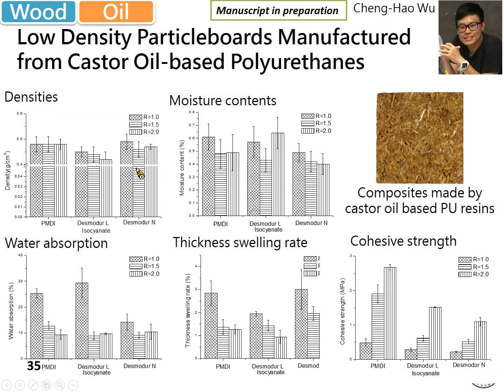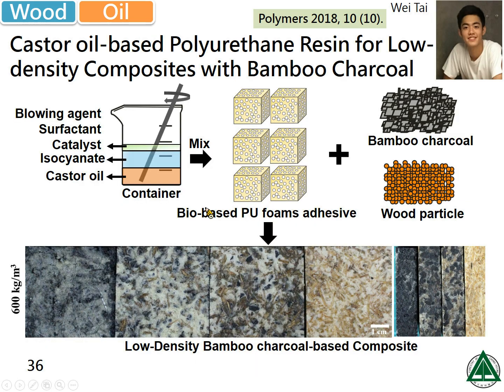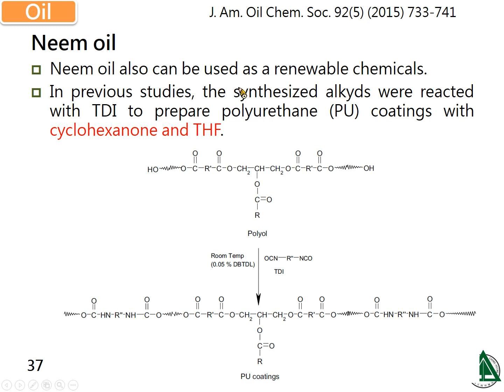The castor oil-based polyurethane foam can be used as adhesive. So with the adhesive, we can manufacture some composites. We also use 3 kinds of isocyanate to prepare it and compare it. We also use bamboo charcoal to prepare composite. The composite has excellent dimensional stability. The result shows the bio-based polyurethane composite has high potential to be used as eco-friendly building materials. Neem oil can also be used as renewable chemicals.